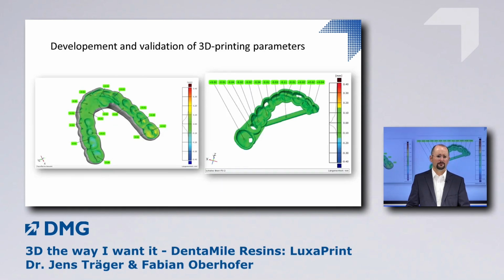And on the right hand side we see a much better object, mostly green, which is inside the tolerance limits. And two more examples I've brought here are from a bite splint on the left hand and from a drilling guide on the right hand side. And in these occlusal surfaces we see the deviation between the scanned object and the initial digital data set or STL file in millimeters, and we can see that we have deviations in the order of 10, 20, maybe sometimes 40 microns, so we can really get highly accurate objects.